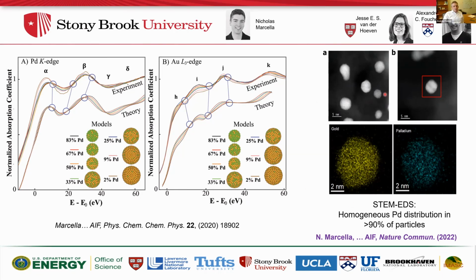But also I wanted to give credit to another component of this research, which is we can't go blind about this kind of very detailed structural analysis, because the homogeneity or heterogeneity is very important to know, whether it is self-similar alloys, you know, from particle to particle, or there is very broad distribution of sizes, compositions, and whatnot. And if you don't know that, average information from XANES or XAFS is misleading or doesn't tell us anything. So fortunately, we had a very good team in our project, with access to excellent electron microscopy facilities. And as you see here, the distribution of gold and palladium was quite uniform within the particle and also across the particles. I don't show it here, but the distribution showed that up to 90% or more were homogeneously distributed.